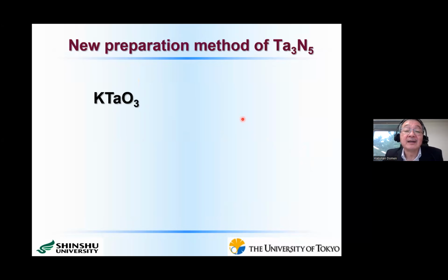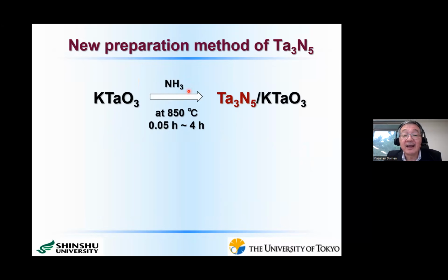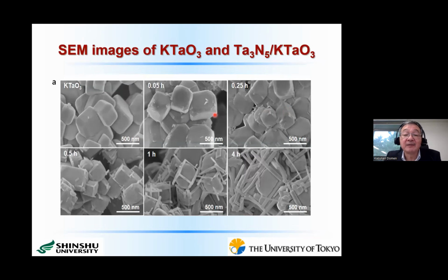However, very recently, we have realized that when we change the starting material from tantalum pentoxide to potassium tantalate, then with nitridation again at 850 degrees C, but for a very short period, 0.05 hour to 4 hours, we can prepare Ta3N5 on top of potassium tantalate. Now let me show such materials. Okay, this is the starting material of potassium tantalate. After 0.25 hour nitridation, I mean 15 minutes nitridation, you see that some nanorods are starting to grow. And after 1 hour, we can clearly observe that these kinds of nanorods exist.